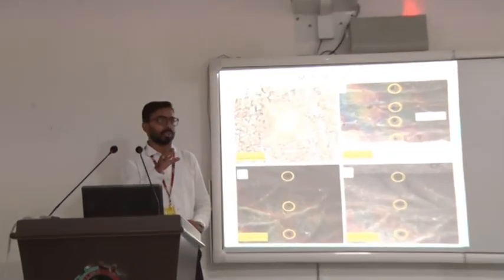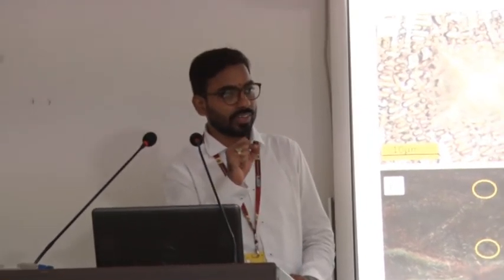Yes, sir. The corrosion test is carried out in similar conditions. The temperature is maintained at 37 degrees Celsius, sir, which is suitable to the human body. Similarly, the biocompatibility cytotoxicity is also measured at 37 degrees Celsius. This is done in a CO2 incubator, sir, where we maintain the temperature constantly for 3 days and measure the cell viability at 37 degrees Celsius.